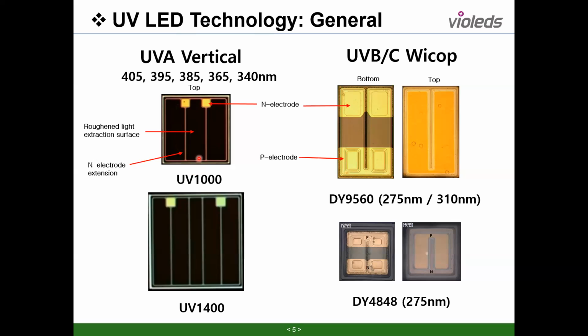And you may have a question: why is it so black? On the previous page, there was the roughened surface, right? The roughened surface is good for light extraction from the inside to the outside. When it looks black, it means that all the light at the surface just goes through to the inside, so no light comes back from there. This is a very roughened surface, and every light goes through directly, so there is no reflection. So we make a very good roughened surface.